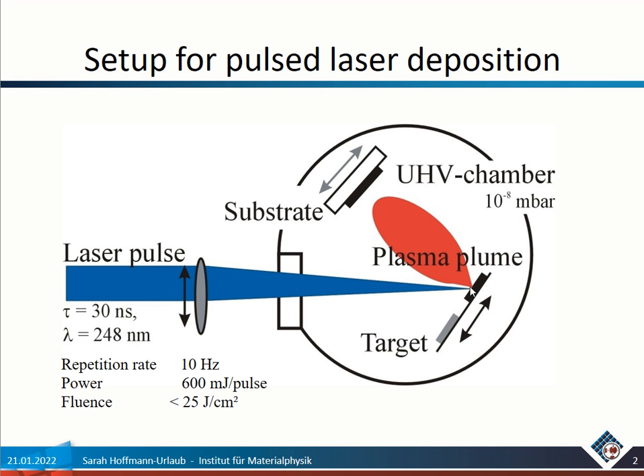Here at the target site, the laser beam heats up the target to a few thousand degrees C, and the material is instantaneously evaporated. This material that's then directly above that target is further ionized by the incoming laser beam, and a plasma is generated that is expanding directly perpendicular here to the substrate side.